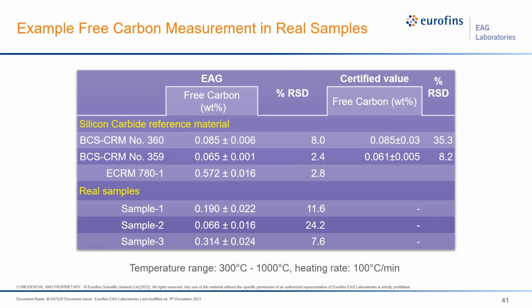Measurement results of free carbon concentration in different silicon carbides as well as real samples are shown in this table. The gas extraction was done between 300 degrees Celsius to 1000 degrees Celsius with heating rate of 100 degrees Celsius per minute. As can be seen for the standard values, our method yields better percentage RSD values when compared to certified reference values. And we have also shown some real sample examples where we were able to measure free carbon at a value of like 660 ppm.